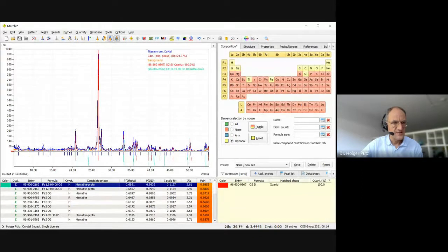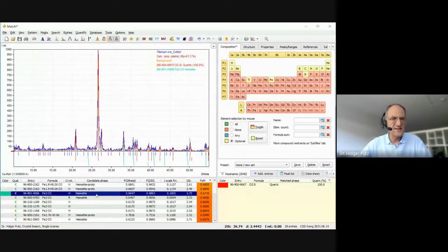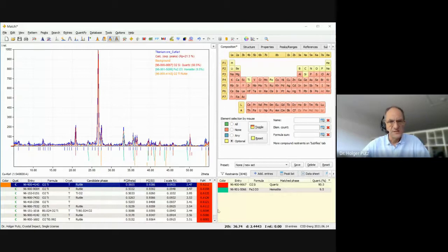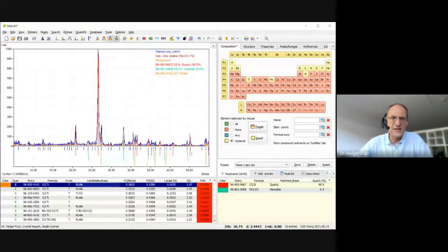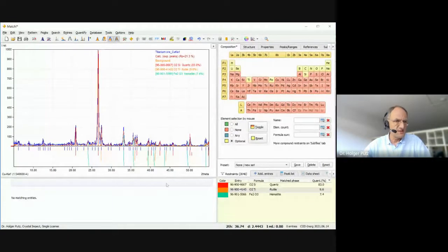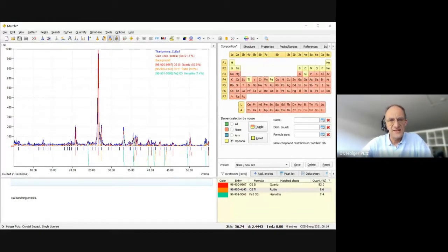And here you see that the next best matching phase is hematite, which is to be expected somehow for this compound. And I would also select it as matching here. But up to now, you see, we don't have any titanium here. And I mentioned that it is a titanium ore. So if you look now at the candidate list, we finally found our titanium in the form of the phase rutile. And yes, I will also select it as matching. And the analysis seems to be finished at this point because no phases are listed here in the candidate list anymore. And just like in the very first example, we now have the list of the phases that are present.